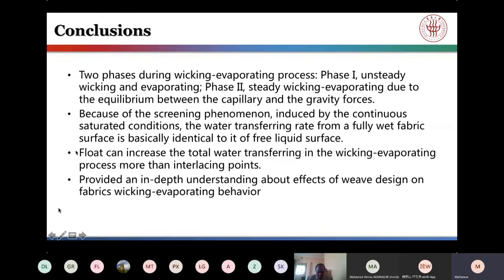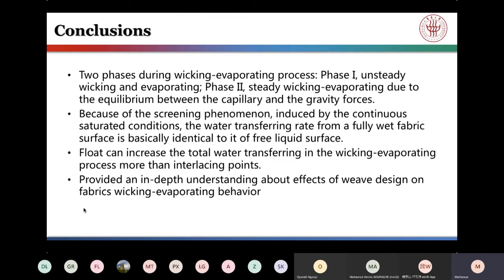Also, in the study, we can see that woven fabric with more float have more micropores, possessing non-uniform capillary channels and more airspace for evaporating. Float can increase the total water transfer in the wicking evaporating process more than interlacing points. Generally, findings in the study provide an in-depth understanding about effects of weaving design on fabrics' wicking evaporating behavior. And in the further study, more weave structures should be considered to investigate effects of the structural and weave parameters on the water transfer. That's all my report. Thank you for your listening.